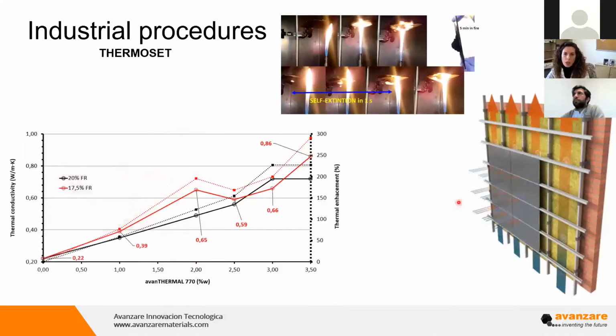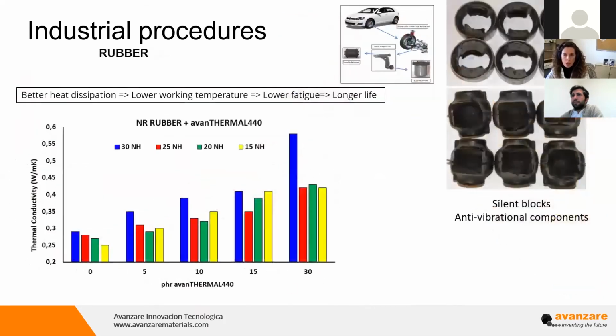Okay. In the case of thermoset, we've seen before the V0 behavior of the polymer with glass fiber, fire retardants, and graphene materials, with these features of self-extinction, valid not only for automotive but also for building. For example, to manage the heat in houses, in passive houses, and this kind of building. In the case of rubber, we've seen before the increase of the thermal conductivity. These applications are especially done for silent blocks used for anti-vibrational components in cars and the automotive industry, in different parts of the car. And what we do is increase the heat dissipation.